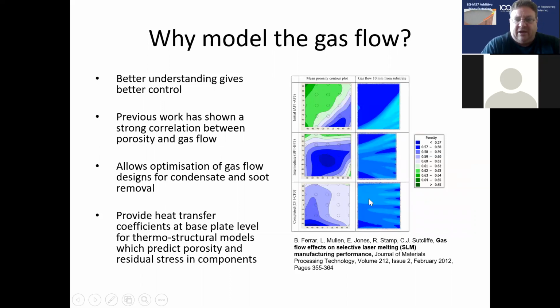So what you can see here on the right-hand side is a paper by Chris Sutcliffe's group on the flow effects on mechanical properties. And you can see the simulation of the flow and the flow rates, and also measurements of porosity. You've got the porosity on the left-hand side, and you see the flow rate on the right-hand side as measured 10 millimeters off the substrate. And you can see how they have correlated.